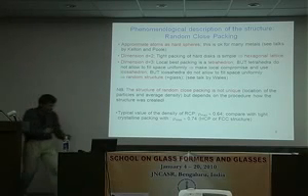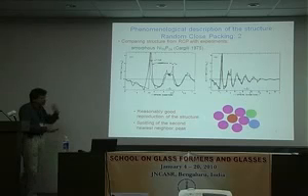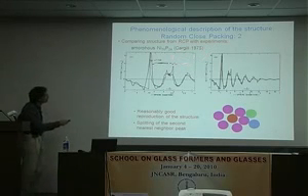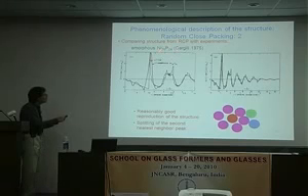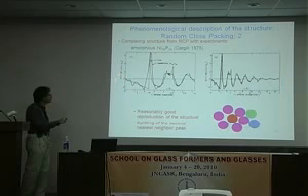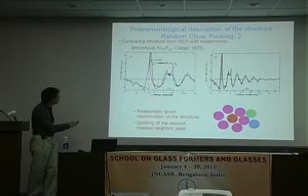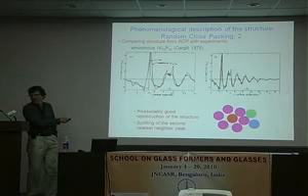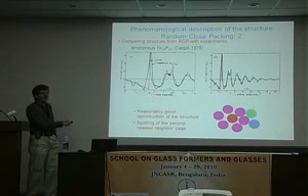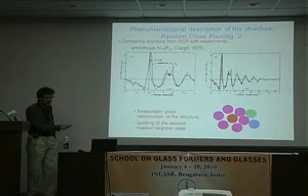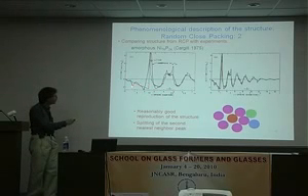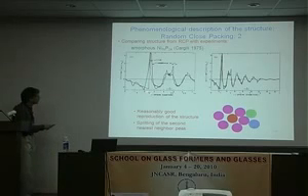Okay. Now, how well does this work? It's a very simple model. Again, these are old results by Cargill. This is a metalloid glass former. So this is the g of r, the nice smooth line. So you have here the first peak. You see, this is a nice example why, at that time at least, they were not able, from the static structure factor, to calculate the g of r, because this here is all junk. Huh? You remember what I said the last time. But here, the things look much smoother.